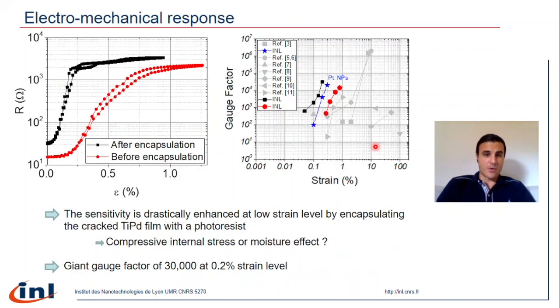The electromechanical response of these crack-based transducers was characterized in a buckling configuration. In order to avoid any effect of humidity, we have encapsulated our crack sensor with a photoresist layer. On this graph, we have compared two sensitivity curves obtained before and after encapsulation of the cracks. On this graph, you can first observe a slight hysteresis phenomenon, which is probably due to adhesion forces or to viscoelastic effect within the polyimide substrate.